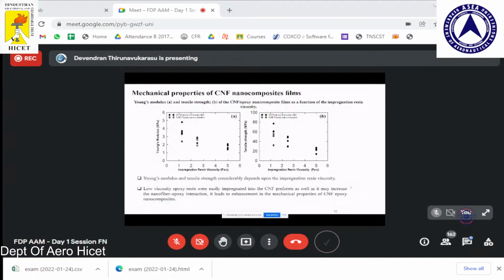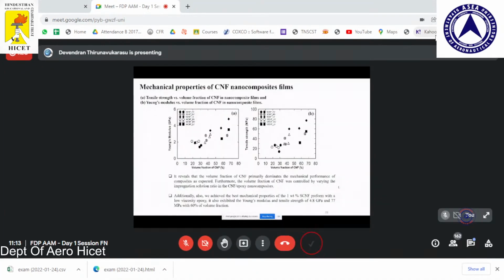The impregnation, as I told, is very good in the lower viscosity resins, and so we can get good stiffness and mechanical properties with low viscosity resins. The same holds for the volume fraction and Young's modulus in the lower viscosity resin systems, and 1% cellulose nanofiber gives good mechanical properties. The volume fraction reaches up to 60%, Young's modulus is 6.6 GPa, and tensile strength is 77 MPa. This is our final result, the best mechanical property for one weight percentage.